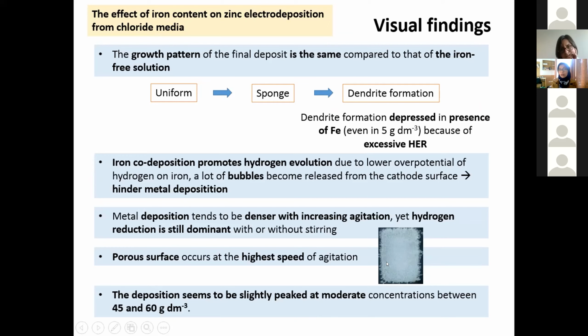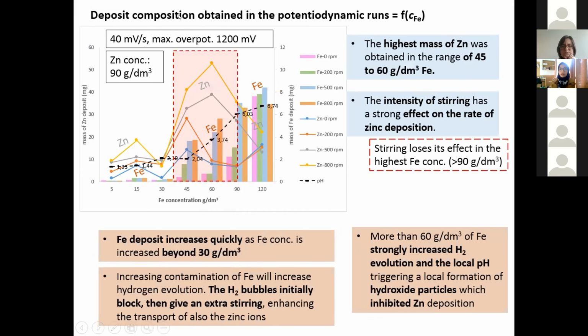Here we can say the hydrogen evolution not only gives us a drawback, but sometimes it gives us a benefit, because it makes a turbulence where we make the composition in the solution uniform. But then let's see the compositions obtained after the potentiodynamic runs with some compositions of iron.